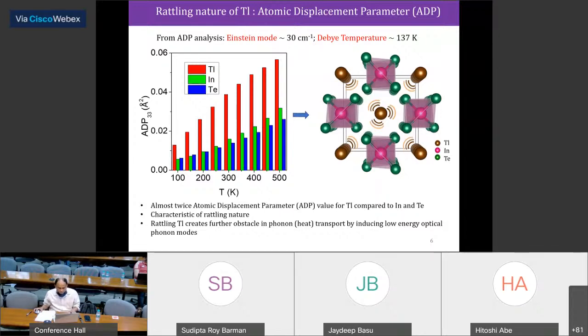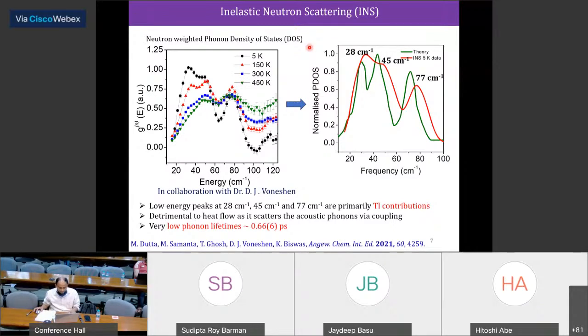So now the question is, can we visualize this Einstein mode by experiment? In order to do that, the next experiment we did was inelastic neutron scattering at RAL, UK. You can see there are low energy phonon modes experimentally obtained, which is very important: 28 inverse centimeters, 45 inverse centimeters, and 77 inverse centimeters. This matches well with our previous JACS paper, where we predicted the phonon dispersion by DFT calculation. These low energy phonon modes are actually coming from the thallium rattler. We have estimated the phonon lifetime from the line width, which is an ultra low value, below 1 picosecond. So the phonon dies down heavily in this system, and that's why we see ultra low thermal conductivity.